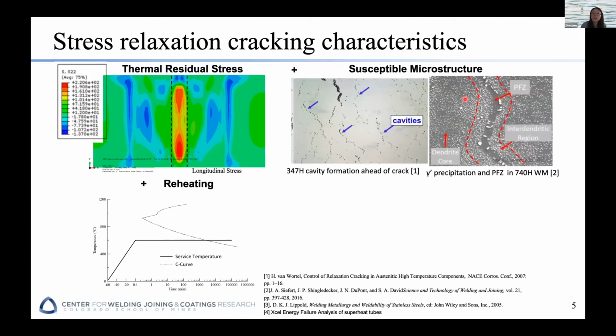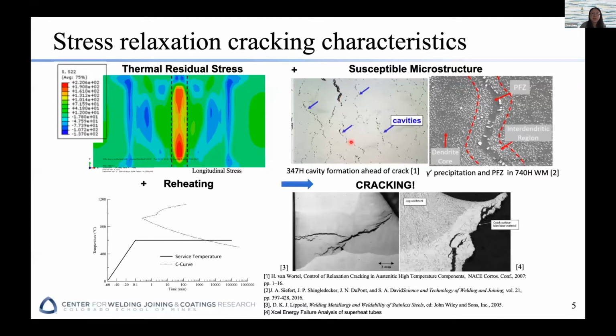Okay, and then when the residual stress starts to relax at this elevated temperature, it will preferentially go into those dark regions that do not have precipitates to strengthen them, because this is a relatively soft region. And when sufficient stress relaxes into this region, you will start to form cavities. Okay, and then eventually you will see cracks forming in this region. So that's the mechanism for stress relaxation cracking.